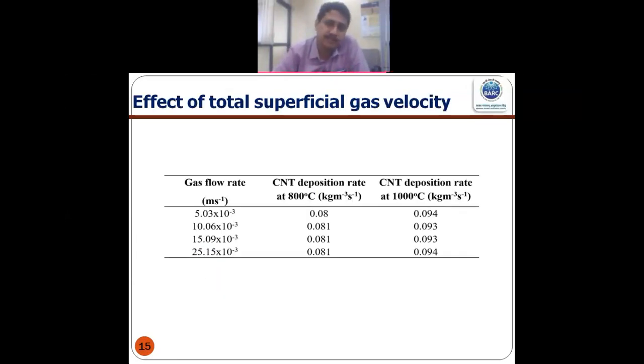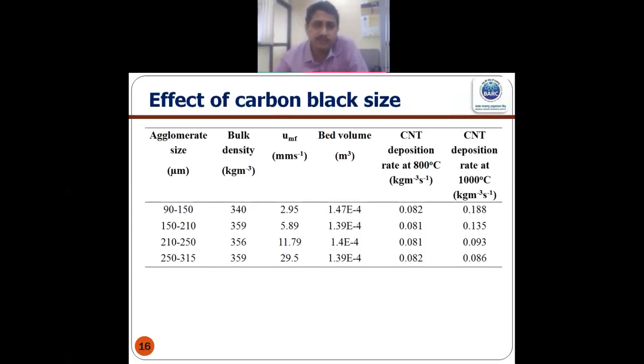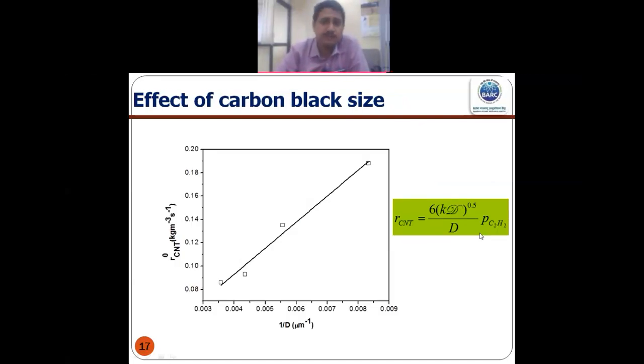So now when we varied the superficial gas velocity, we saw that there is not much effect on the CNT production rate, both below that 800 degrees centigrade, and another above that, at 1000 degrees. In both cases, there was not much effect. So we can conclude that there is no effect of external gas transfer. But when we varied the carbon black size, at low temperature, that is at 800 degrees centigrade, there was no effect, but at high temperature, that is at 1000 degrees centigrade, the CNT deposition rate was varying with the size of the carbon black. So now if I plot them, we can get a straight line, and by fitting this equation, we can get the values of the rate constant as well as the diffusivity value for this particular mechanism.